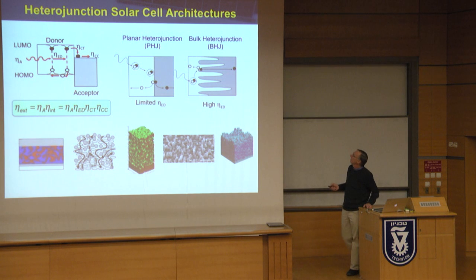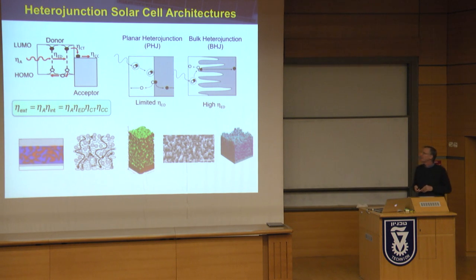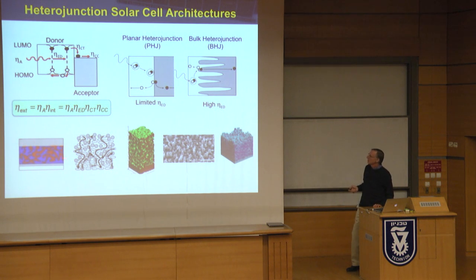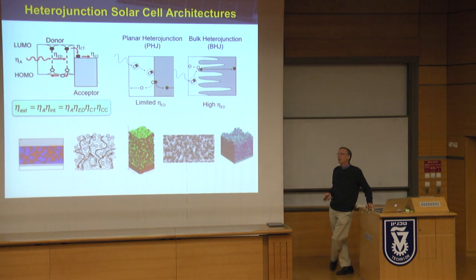Now in the polymer world, it was really Alan Heeger who demonstrated the first bulk heterojunction device, where he took 2 polymers which were partially miscible, and they separate into donor and acceptor and form this kind of entangled structure, so that in a sense it separates the dimensionality of the problem into two dimensions. The photon can be absorbed along the fingers, but the exciton only has to drift sideways.